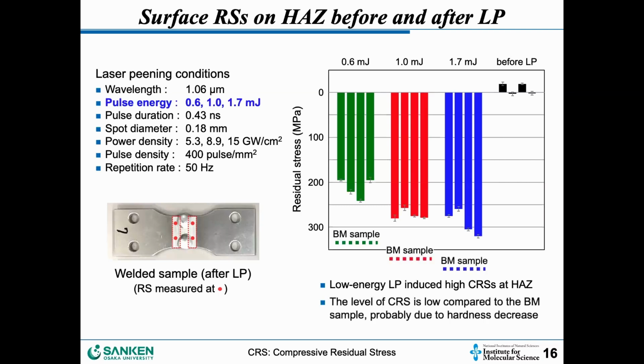However, this one is the residual stress value of the base metal sample. I think laser welding may decrease the hardness of the material. That's because we cannot induce higher compression compared to the base metal samples.